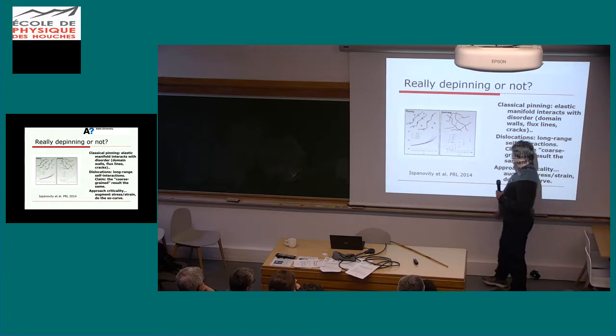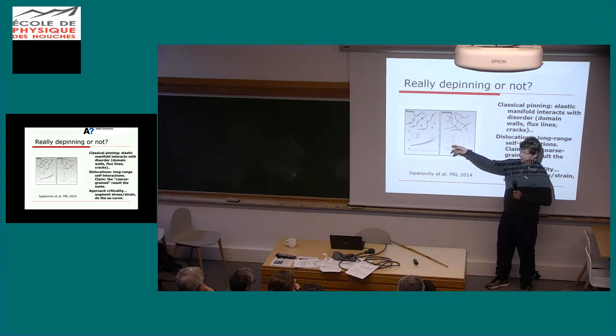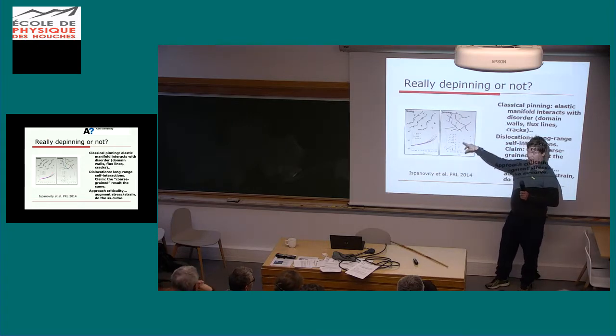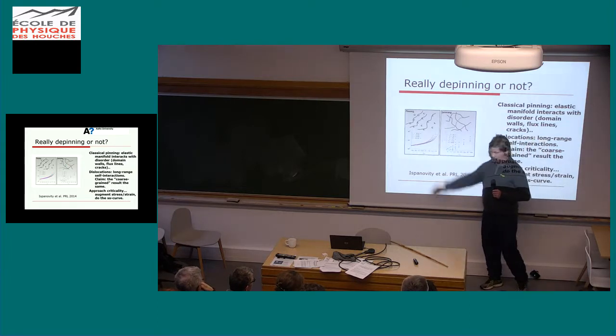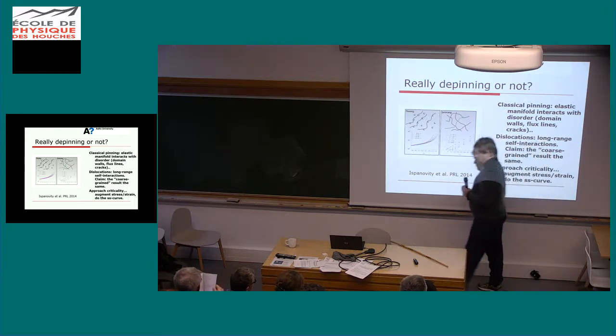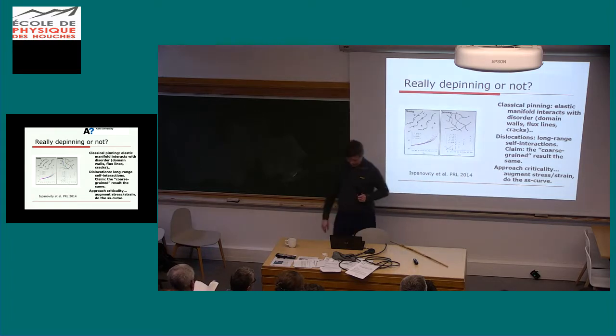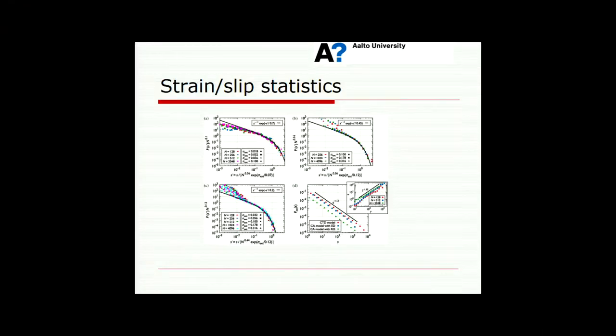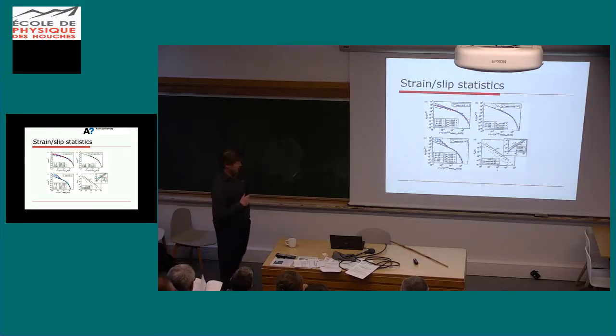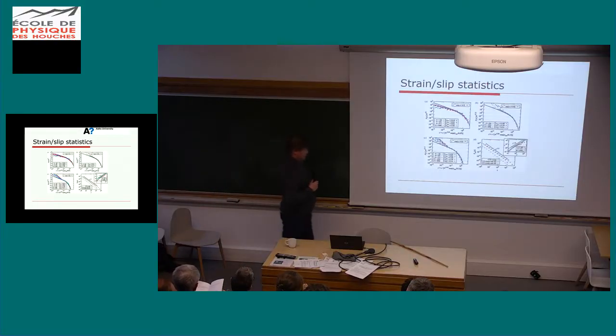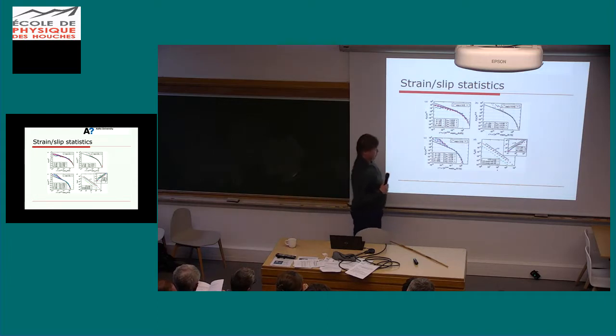To make a long story short, now if you do these models of two-dimensional dislocation systems, you see that the avalanche sizes actually do not follow that kind of behavior at all. You get an exponential increase as a function of the number of particles in the system, such that there's an amplitude here, and that does not really look like that at all. So something else happens, and what else happens? Well, of course you still get scale-free behavior, but you get the scale-free behavior at any stress applied, so it's completely different from a typical critical point.